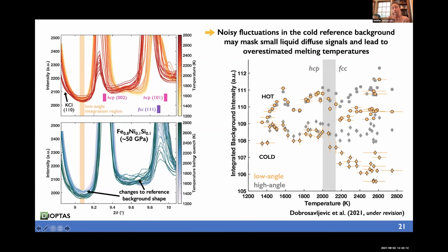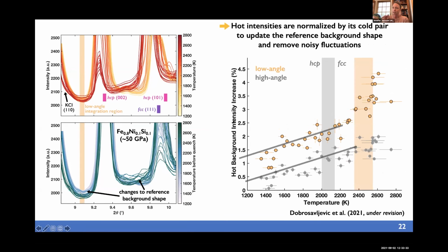Finally, in the next couple of slides, the evolution of the hot spectra is shown here on the left, and with the pairs of cold spectra, you see the changes to the reference in the background shape can make it very difficult to detect small levels of melt. And you see the scatter on the right. However, by using pairs of these X-ray diffraction patterns, we can now see a clear deviation from just a general heating trend. And this is what we use to detect melting.